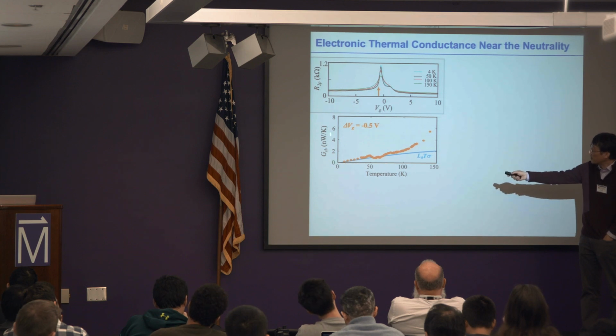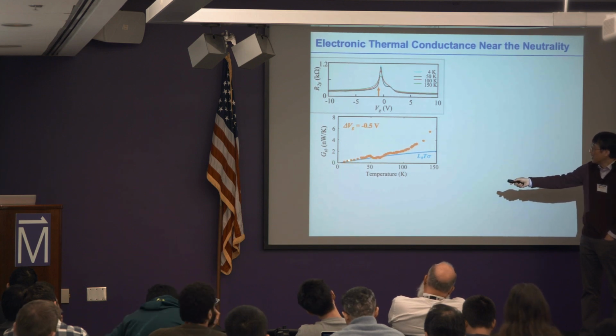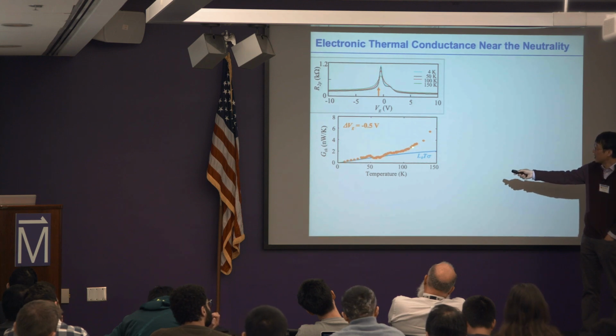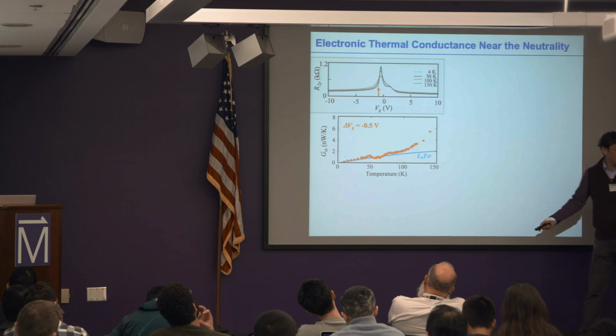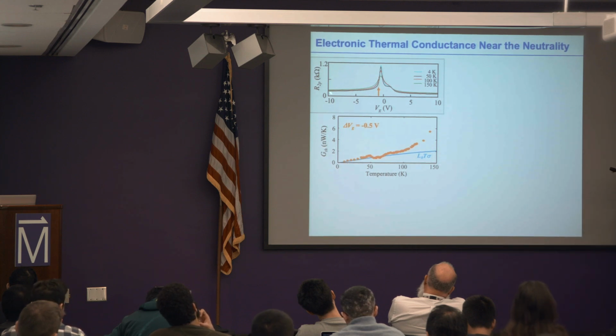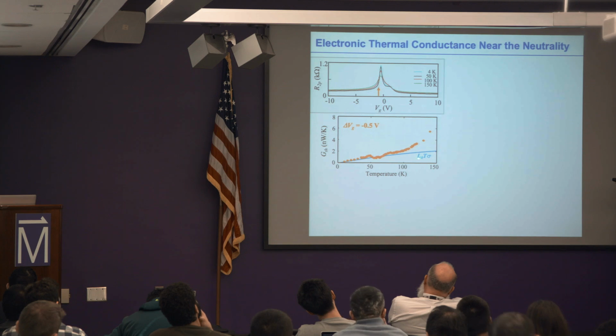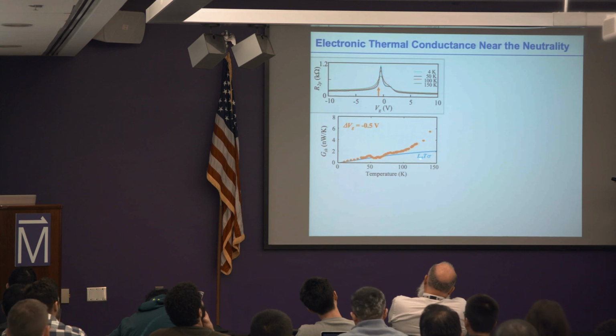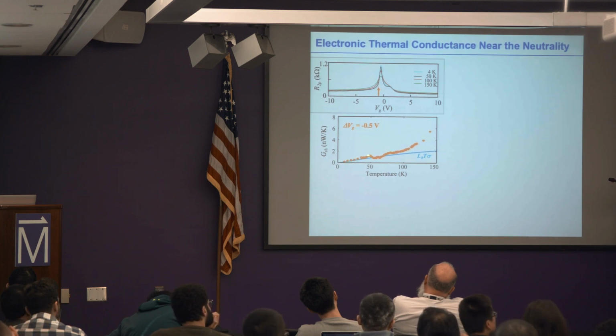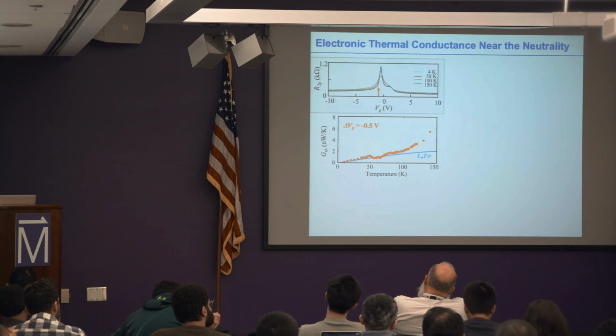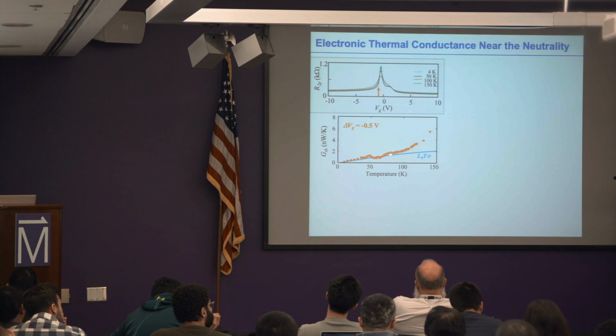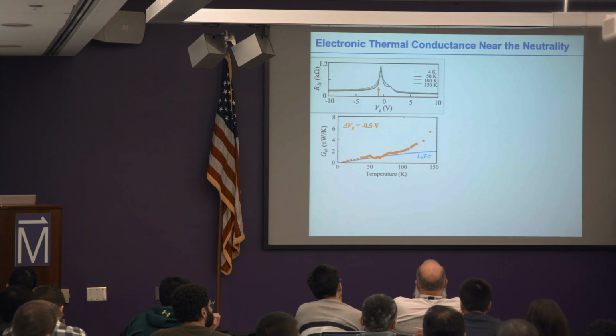So I'm showing here the thermal conductance that I measured as a function of temperature. It stays more like constant and then goes up. For comparison, to see how well it matches the Wiedemann-Franz law, I take this thermal conductance, convert the electrical conductance, multiply with the Sommerfeld value and T, and replot against temperature. This is the line going through the electrical conductance times the Sommerfeld value. If the Wiedemann-Franz law works, the orange curve and blue curve should exactly overlap. What you see here up to something like 100 Kelvin, there's some deviation here and there, but at least it's reasonably close.